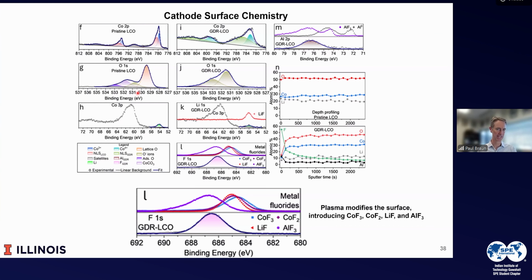To understand what the surface is, we did a lot of XPS. I won't go into all the details, but what it does is it modifies the surface, introducing various cobalt fluoride phases, lithium fluoride, and aluminum fluoride. So this gradient disordered rock salt contains a mixture of cobalt, lithium, and aluminum in fluorides as well as oxides. And so it's a complex structure because it contains fluorine and oxygen on the anion sites and cobalt, lithium, and aluminum on cation sites.